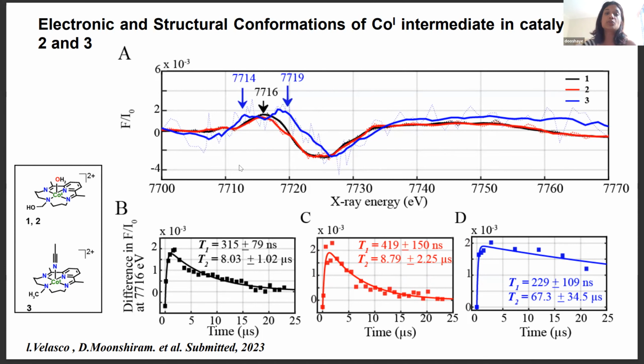And expectedly, catalysts 1 and 2, which adopt the same structure after dissolution in water, have a transient signal at the same energy at around 7716 eV, but that of catalyst 3 has two different peaks, showing that it has a slightly different structural conformation than the other catalysts. And as well, we were able to monitor the kinetics of the cobalt-1 intermediate, and you will see that the kinetics of the formation and the decay of the cobalt-1 species is the same in complexes 1 and 2. However, it is significantly longer in the one with the methyl group.